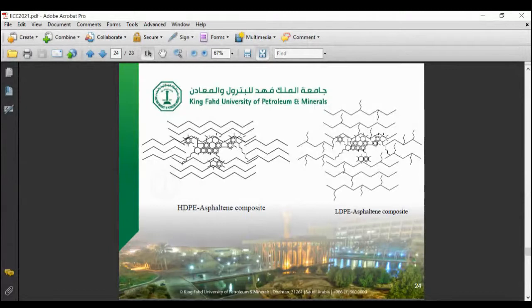This is a general model. When we use asphaltene with the HDPE, high density polyethylene, and low density polyethylene, and after using these composites, we try to find out if there is any effect on the strength of these polymers. And you see, when we compare the virgin HDPE with the composite and the LDPE with the composite, the mechanical strength property, whether it is elongation or the tensile, they increase much. They showed higher values than the virgin HDPE and LDPE.